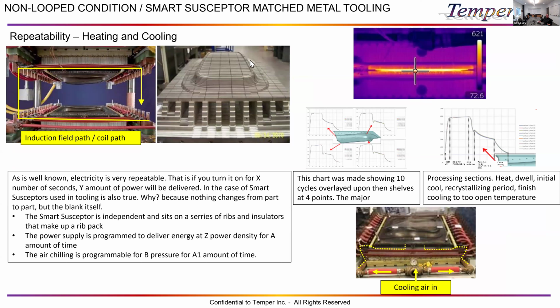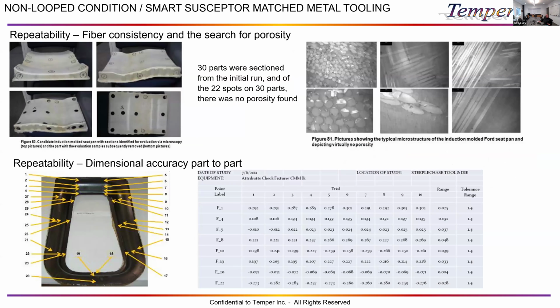And then it's supported by a rib pack, and then it's cooled via compressed air, which gives you a very quick drop. We're in the 400 to 500 degrees per minute on the cooling, and actually 600 to 700 degrees on the ramp. We've done a lot of studies on density, repeatability,